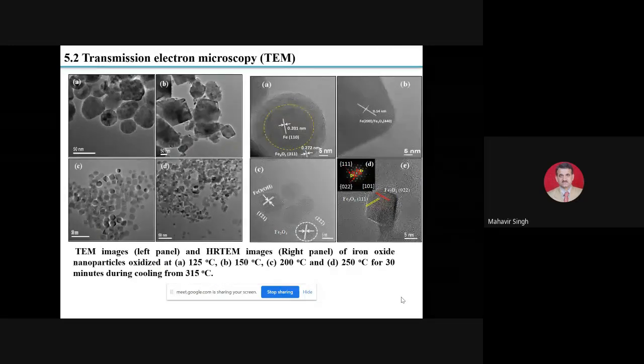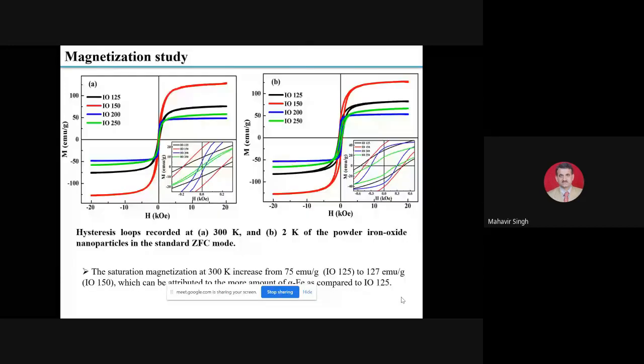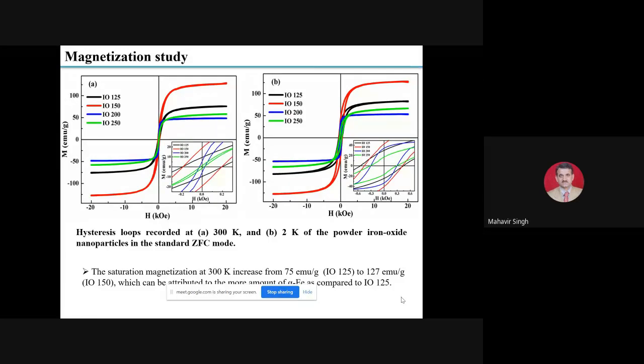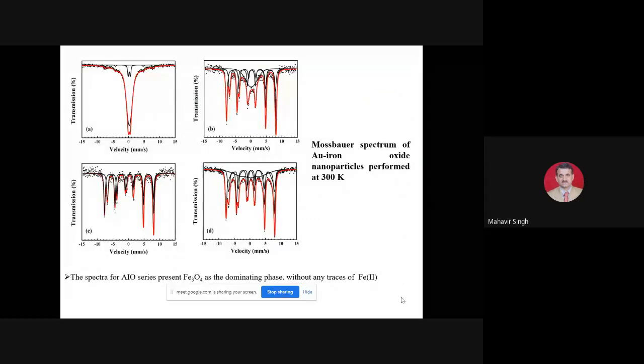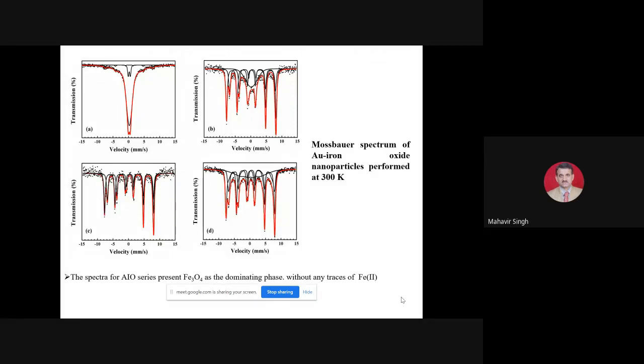So this is the HRTEM. So this is SPM. Clear, this is SPM having coercivity close to zero. So as I mentioned, dear friends, if you want to use it in any kind of application, we have to achieve SPM. Anyhow, we have achieved it in a closed environment, that is in the presence of argon and vacuum. So this is the Mössbauer. There is clear indication from a six line pattern to a doublet, meaning shifting from bulk magnetic nanoparticle to single magnetic nanoparticle or even at SPM having a doublet.